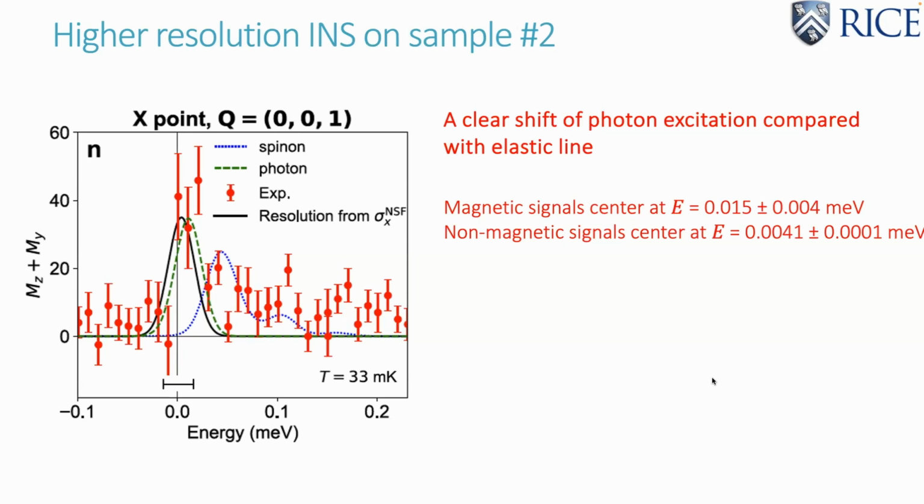Yeah, so the argument we have is, because we clearly see the Q dependence of the scattering, any impurity-induced intensity would be uniform around K space, right? But we see clear Q dependence in our site. I think it's essentially confined to the low boundary. And that's one argument.